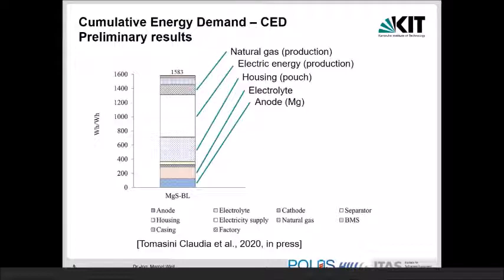And if you look at this not optimized baseline scenario that we have for this cell type, we have different contributions to the overall impact. And you can easily identify that natural gas has a certain contribution. The natural gas is used for the production of the cell, the provision of heat for the production of the cell. Then electric energy for production is the biggest contribution. The housing, that means in this case the pouch of the cell, the electrolyte really has a big contribution, and also the magnesium itself.